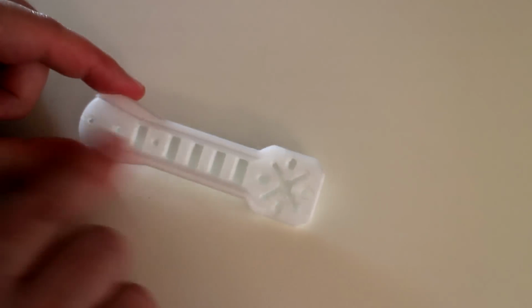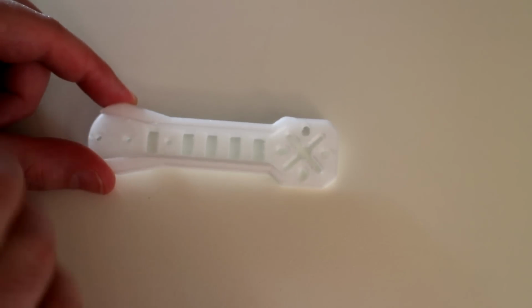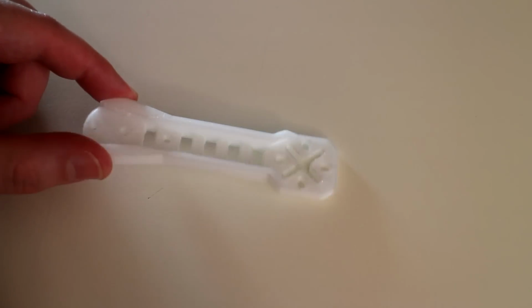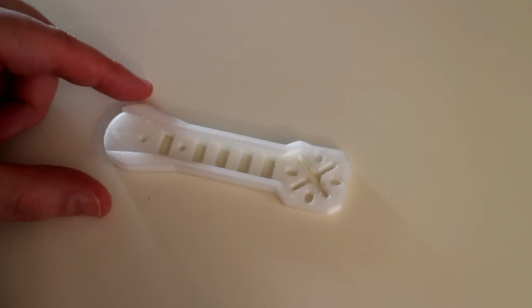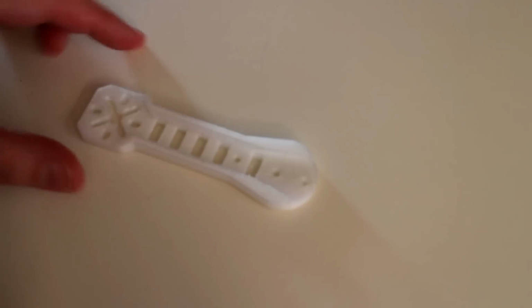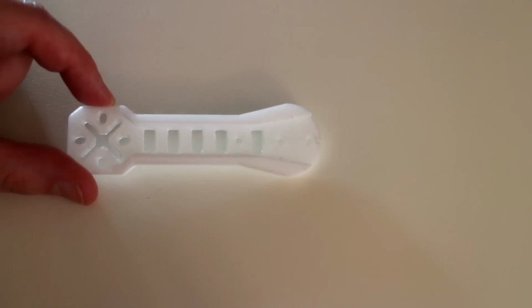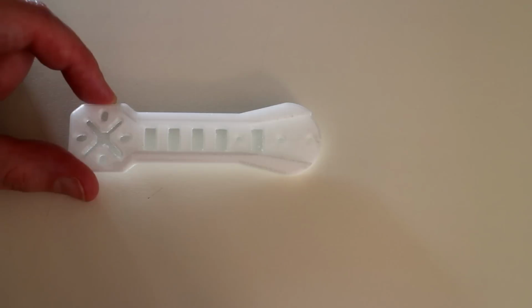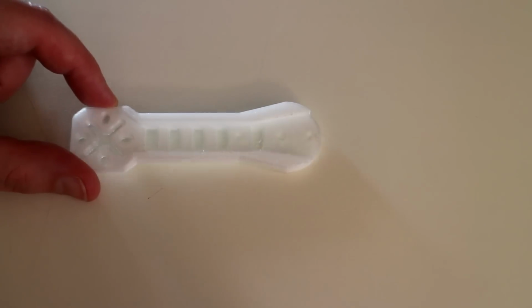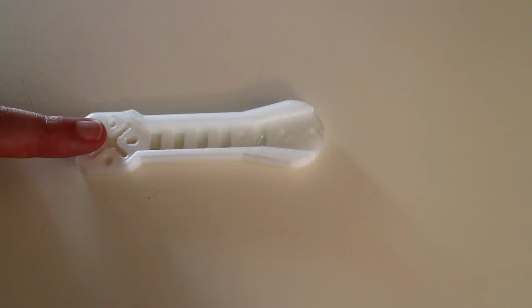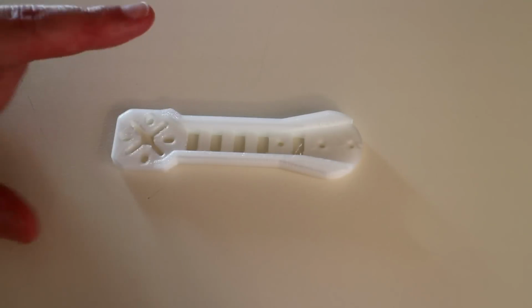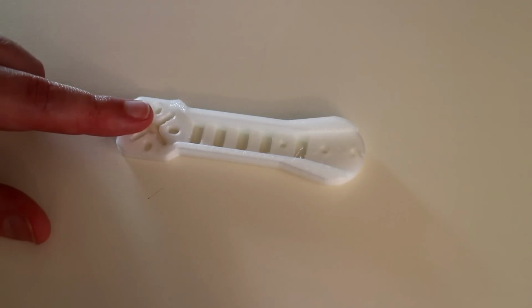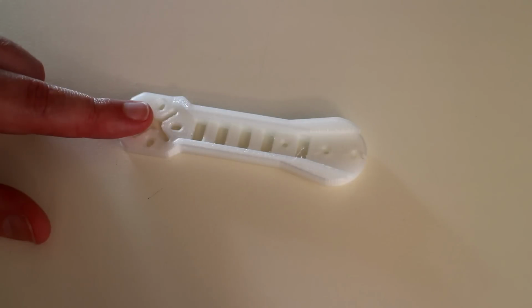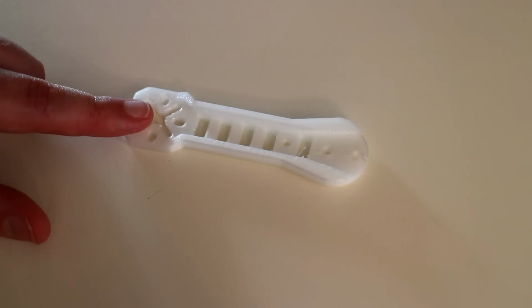The other disadvantage I noticed with this was it was oozing just a little bit more than what a PLA or ABS filament would ooze. Now, normally, if you experience oozing, for me anyway, I would drop the temperature of the hot end while printing. However, I was printing this at 245 degrees Celsius, which is the lowest recommended temperature, so I'm not sure if I can go lower than that and still extrude this filament.